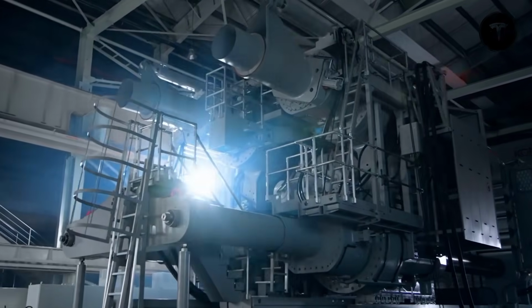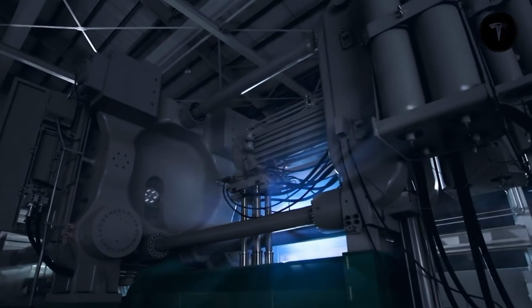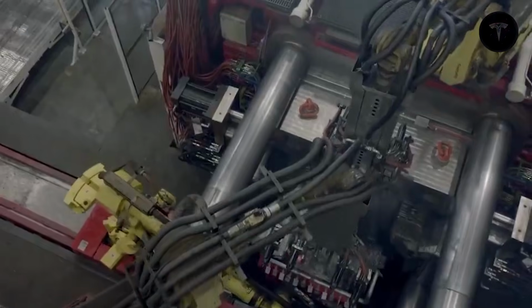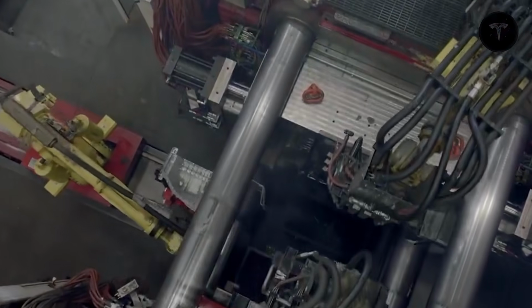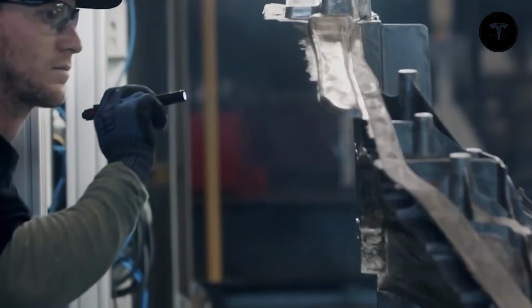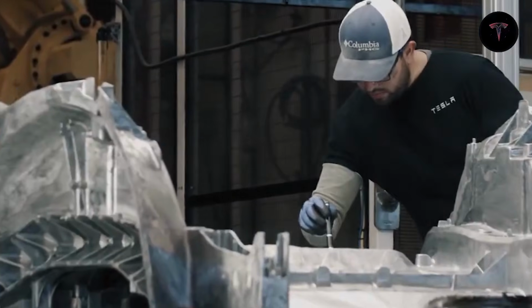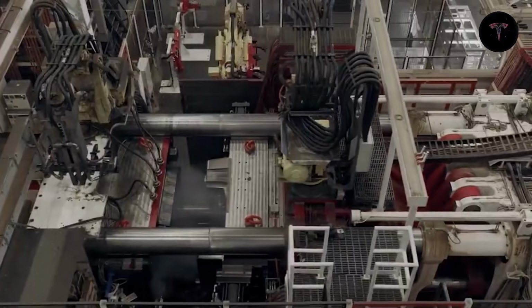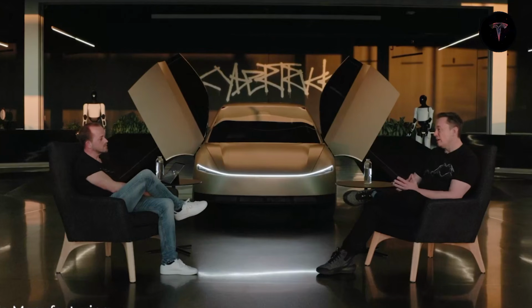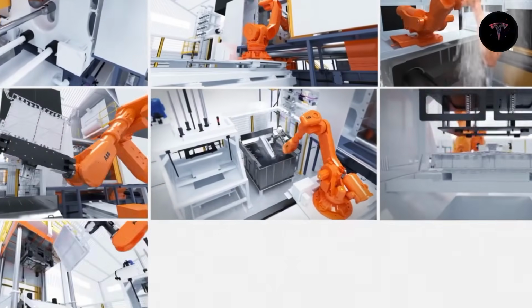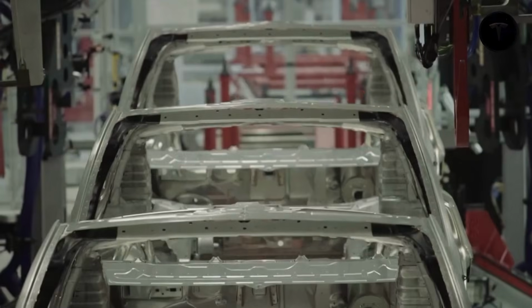Aluminum, a combination of fresh ingots and recycled material from prior casting trimming, is melted at approximately 850 degrees Celsius in a natural gas-powered furnace, then transferred into a sealed electrically heated holding furnace maintained between 750 and 850 degrees Celsius. The holding furnace is blanketed with nitrogen gas to prevent the molten aluminum from oxidizing before the shot. The alloy is further cleaned using argon gas, a rotary degasser, and a silicon carbide filter that removes dissolved gases and particles larger than 25 microns, a level of melt preparation that directly determines whether the finished casting has internal voids or inclusions.